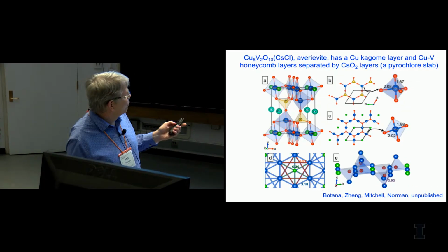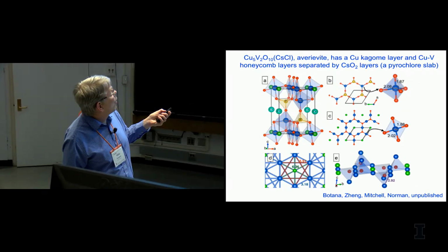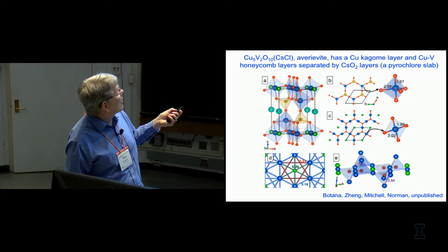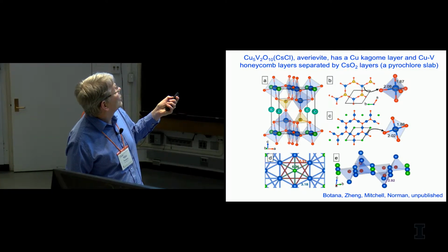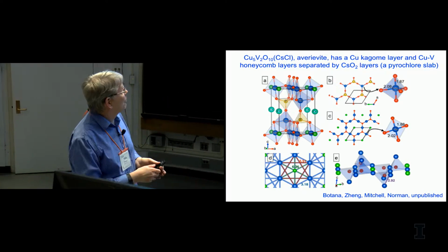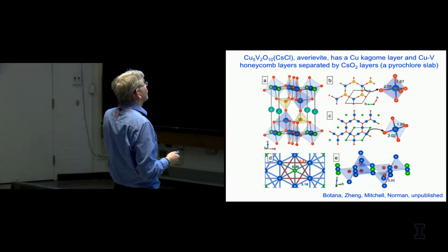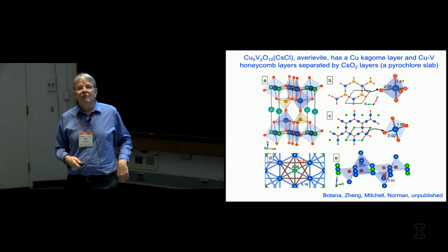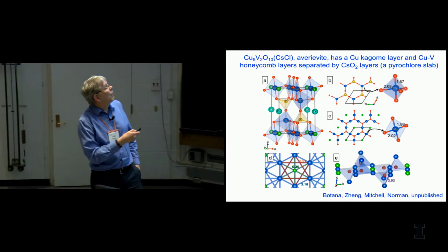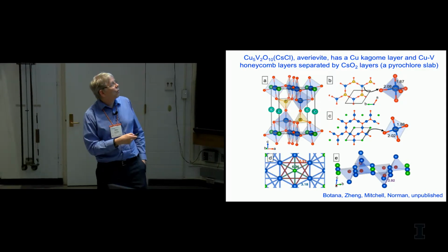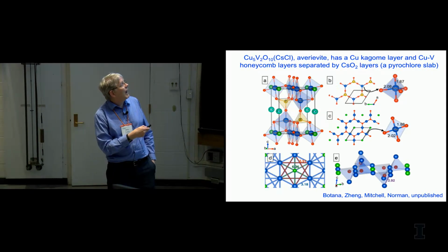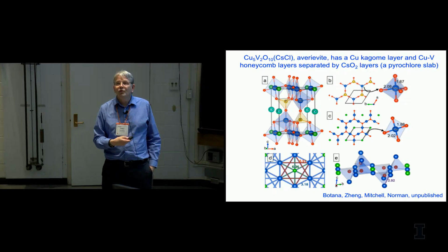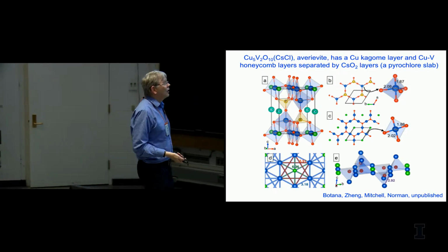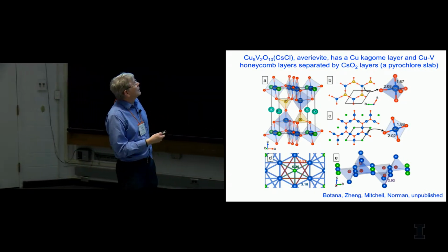And we have this new material, so the question is, can you do kagome for a copper oxide lattice? And the answer is yes. We found this material by looking through the mineralogical database. It was found in some volcano in Kamchatka, but because it's an oxide, it can be grown. It was grown by John Mitchell's group. And in fact, if you grow this material and dope it with zinc like herbertsmithite, you get a quantum spin liquid out of it.